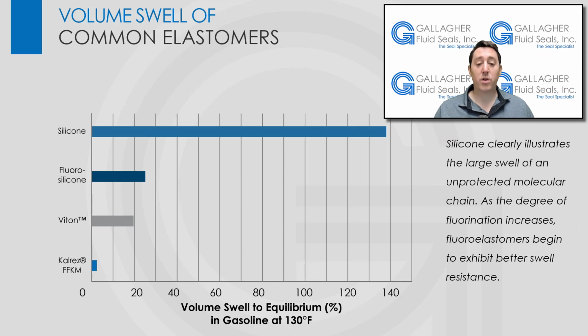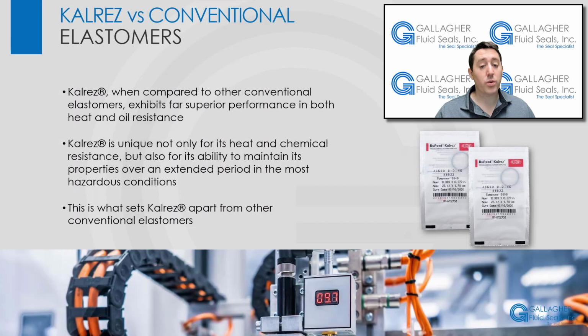Elastomers which swell over 15 to 20% in a chemical media are not suitable for most O-ring applications because standard grooves do not have enough free volume to accommodate the swollen ring. Kalrez, which is fully fluorinated, hardly swells at all in this example of aromatic fuel or almost any chemical media. Kalrez, when compared to other conventional elastomers, exhibits far superior performance in both heat and oil resistance.